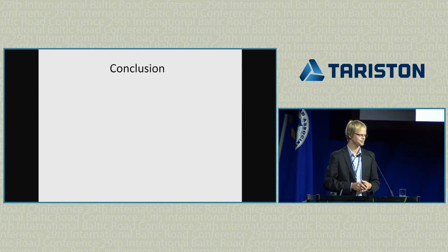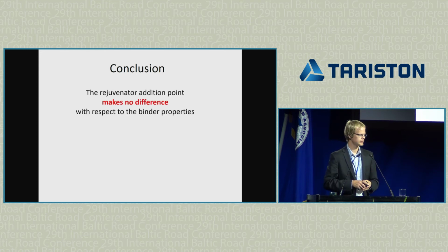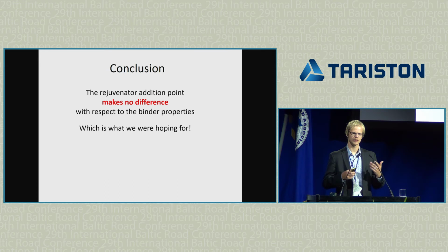Okay, so now the conclusion. And it's very simple. The rejuvenator addition point did not make any difference with respect to the binder properties. So regardless of whether we added it to the cold wrap or to the hot wrap, the effects on the binder were the same. It took me quite a lot of effort to find this out, right? We produced tons of asphalt mixture in an asphalt plant. We did all this extraction work and testing. But actually, the conclusion that we don't see any difference is a good one, because we know that it's not worth adding the rejuvenator before heating of the wrap.